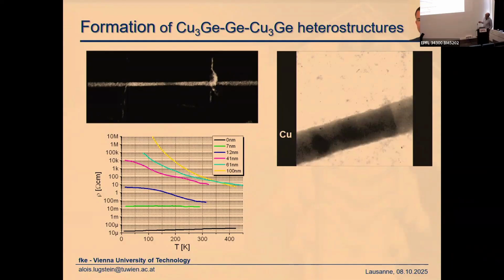And what is shown here is the resistivity as a function of temperature. For this rather long device with 100 nanometer, this behaves nicely as a semiconductor. So you see resistivity decreases with increasing temperature due to the formation of electron-hole pairs. And if it gets shorter and shorter, particularly for the ultra-scale device with only 7 nanometer, there's no dependency on the temperature, which is already an indication of ballistic transport in this super short device.